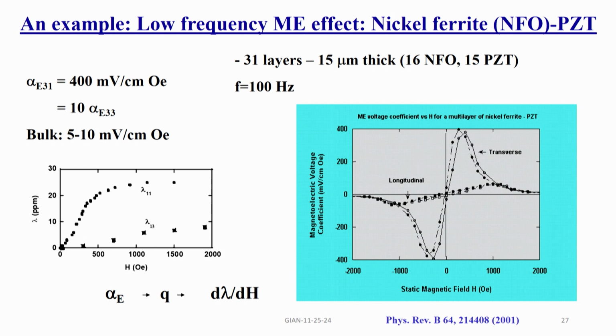Then we measured the voltage coefficient. As you see here, as you increase the bias field, this is for a constant amplitude of the AC magnetic field applied at 100 hertz, and these are the voltage coefficient for magnetic field, both AC and DC, parallel to the sample plane, and it was initially poled perpendicular. So the voltage was measured across the thickness. The voltage coefficient is in millivolts per centimeter Oersted.